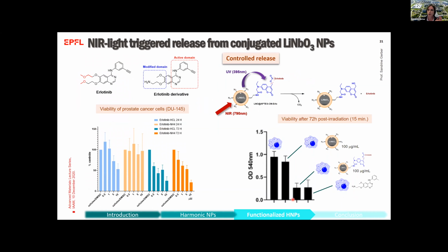Then we went to the controlled release, but first we had to verify that the erlotinib derivative is able to induce the same inhibition as the commercial drug. After 24 hours, this was not observed, but after 72 hours of exposure, you can see that erlotinib, the commercial drug, and our derivative result in quite similar activity toward the inhibition of cell growth.